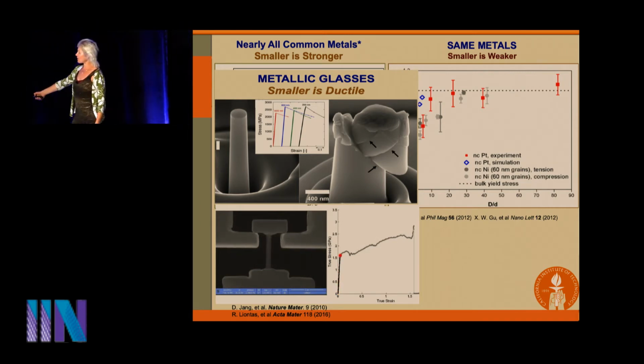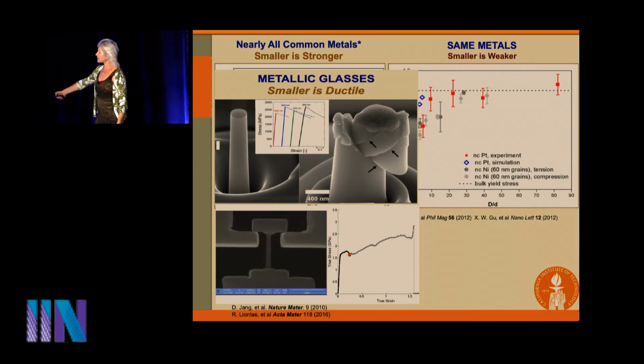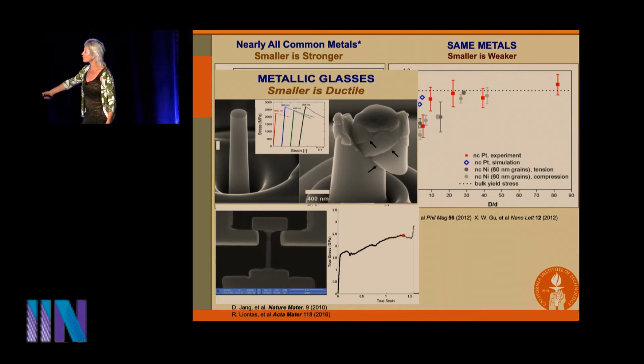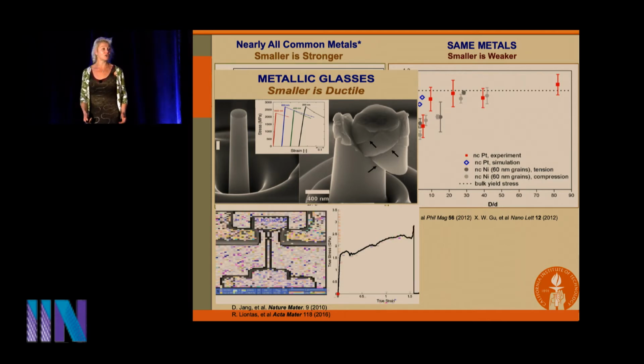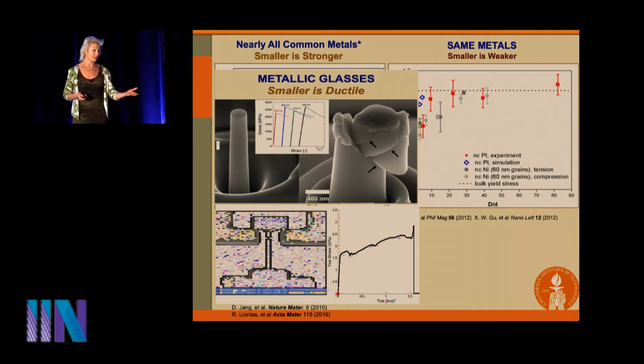So if you look at the stress strain data that we're collecting simultaneously, and especially if you focus on this region, you will see the formation of a neck prior to failure and an extendability of about 100%. So at the nanoscale, it turns out at room temperature, you can actually pull on a glass rod and it thinks that it's behaving like a metal.